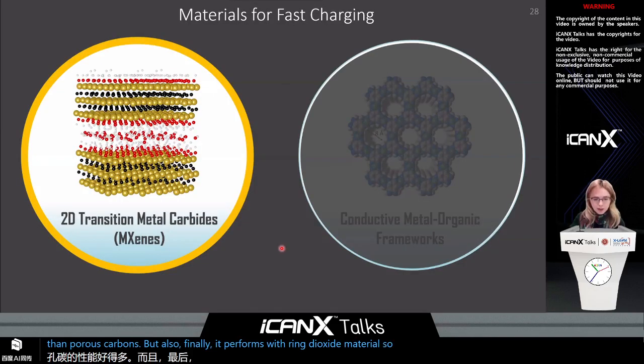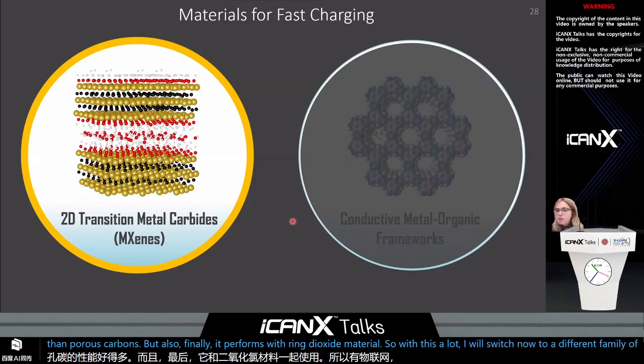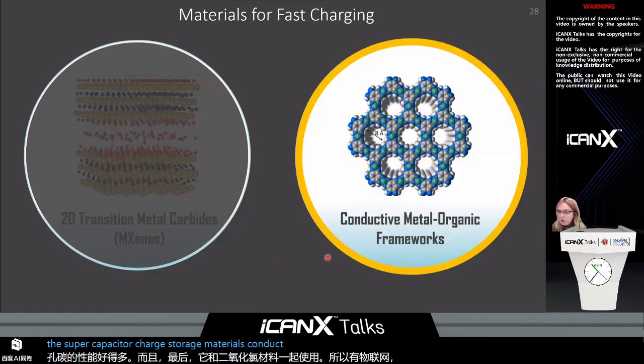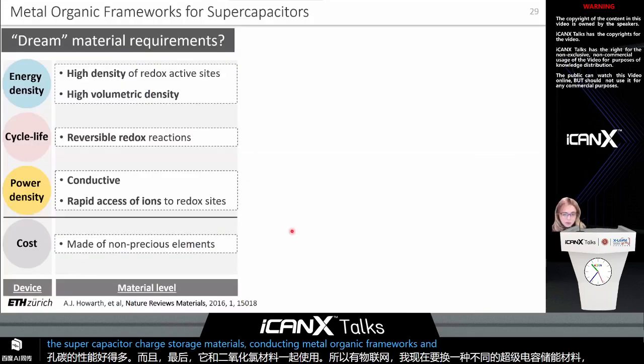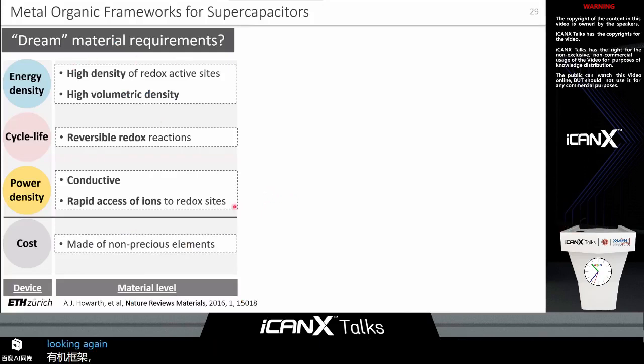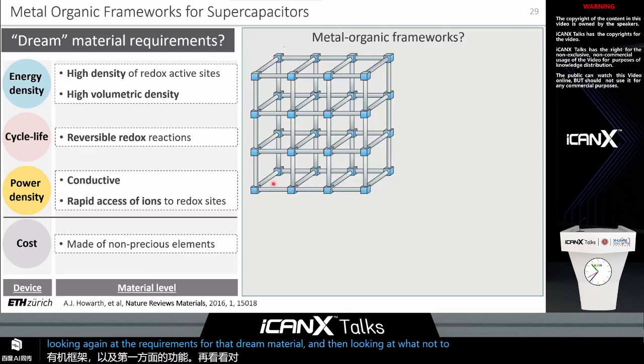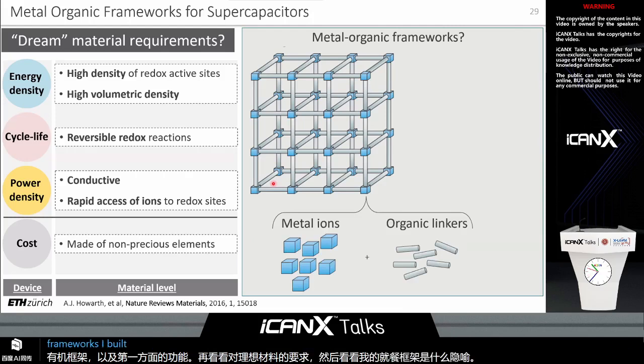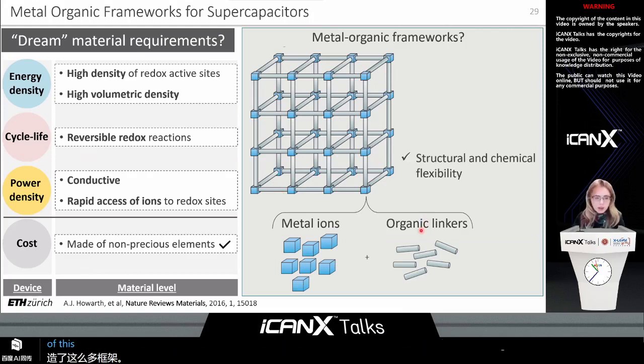So with this note, I will switch now to a different family of supercapacitor charge storage materials, conducting metal organic frameworks. To look into this section, first we start with looking again at the requirements for the dream material, and then looking at what metal organic frameworks are. Metal organic frameworks are built from metal ions coordinated by organic linkers, and this construction allows exceptional structural and chemical flexibility of these materials, and therefore allows us to select the ones which don't feature any precious elements.